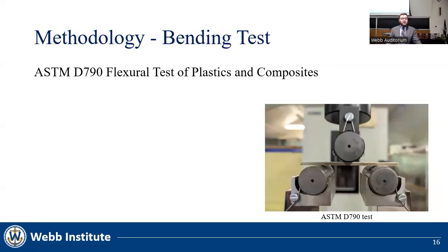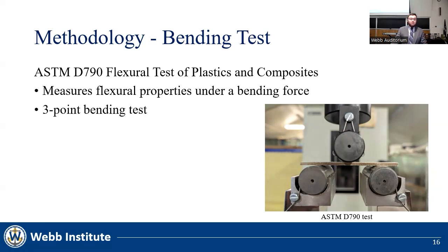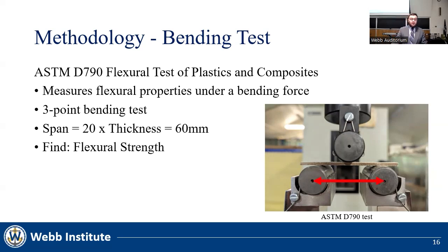For the bending test, I utilized the ASTM D790 flexural test of plastics and composites that can be seen here. It measures the flexural properties under a bending force. It is a 3-point bending test where the span is 20 times the thickness, or 60 millimeters. The goal of this test was to find the flexural strength of the composite.